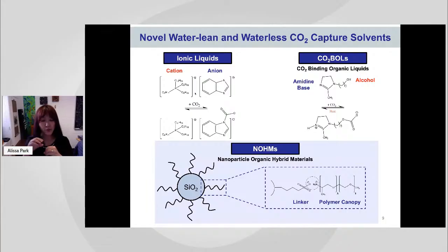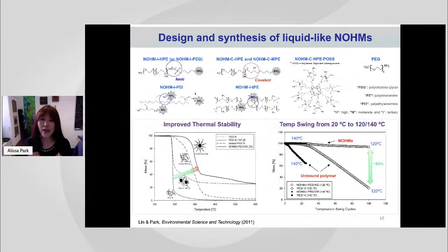In addition, by putting in the right grafting density and right size of these polymers, we may be able to not only control the enthalpy interaction of CO2 with the functional groups along the polymer chain, but maybe we can also control the entropic effect of CO2 capture by frustrating all these polymer chains. So for the first generation of NOHMs, we actually made them without any amine functional groups. We wanted to see the contribution of entropic effect versus enthalpic effect on CO2 capture.